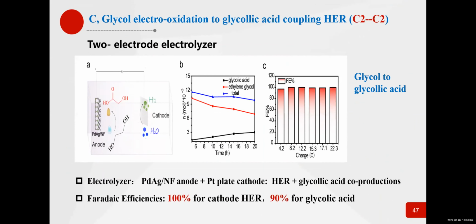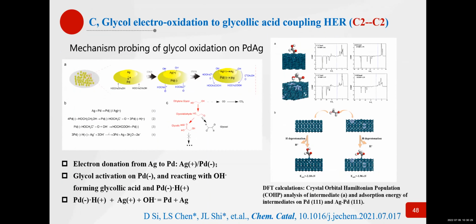And then we have established an electrolyzer for the hydrogen production and for the glycol oxidation to glycolic acid. It shows 100% Faraday efficiency for the HER and 90% Faraday efficiency for the glycolic acid production at the anode. And here we also plot the mechanism why this kind of nanorod shows enhanced activities for the glycol oxidation.